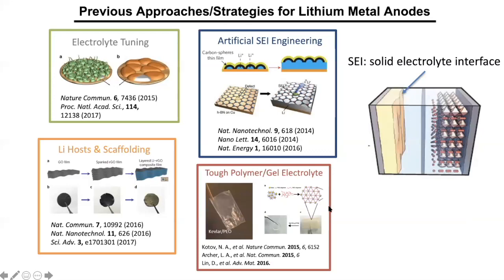And there are many approaches that people have been exploring to try to eliminate the issue of forming the dendrite. Since the lithium is in contact with electrolyte, they try to change the chemistry of the electrolyte so that dendrite is difficult to grow. And they put a protecting layer on the surface to prevent dendrite growth. They put a host to hold the lithium, so that provides some protection. And then also people have used a polymer coating on the surface. It can be called a solid electrolyte interface, can be an artificial one. And people try to put a polymer layer that's very, very strong, so that if you form a dendrite, this dendrite cannot penetrate through this polymer layer and then prevent the shorting.